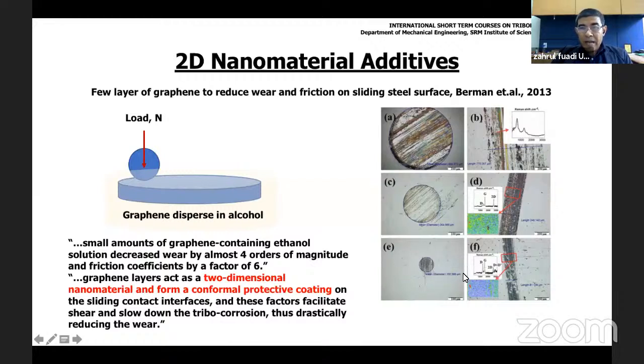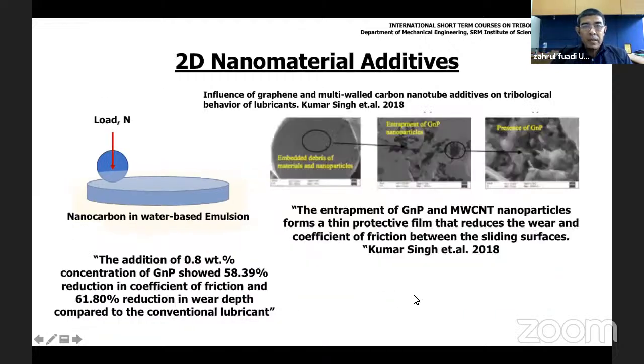Then every 400 cycles, you add some more graphene. So this one you add only once and use, and this one is with intermittent adding, like after several hundred cycles, you add some more graphene, and then after several hundred cycles, you add some more graphene, like that, so that the tribolayer here is produced and then disappears, and with new graphene added, it can be produced again.